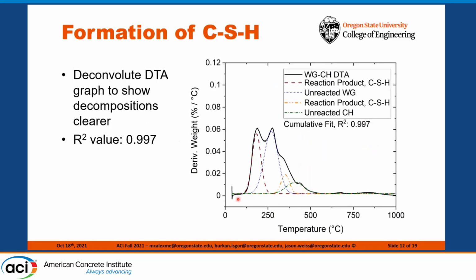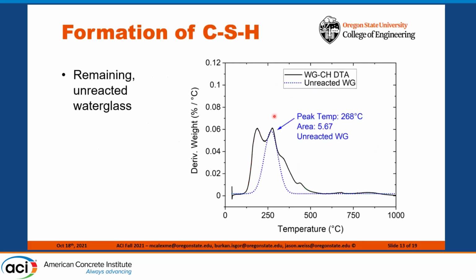We can also take the derivative curve and deconvolute the peaks to see the decompositions more clearly. For this graph, the cumulative peak fit curve has an R² value of 0.997 when compared to the original, which is a pretty close fit. Looking at the individual curves, this one is going to indicate the remaining unreacted water glass in the system. The area under the curve correlates to % weight loss, or the grams per 100 grams binder remaining in the system. This system started with 79 grams of water glass per 100 grams and is now down to 5.67.